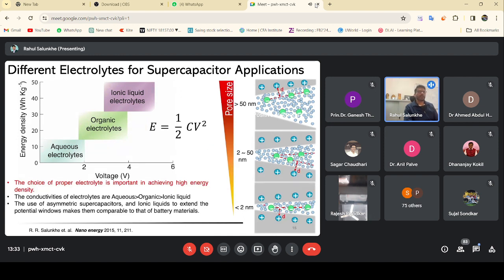So the very first requirement is the micropore structure, and that the ion size should match the pore size. When the ion size matches the pore size, we can achieve a very high capacity for any electrochemical device. This is not only true for carbon materials or non-aqueous electrolytes. This is possible for H2SO4 as well as any metal oxide. So if we take any material with a pore size matching the electrolyte, then your performance is going to be very high. This is the basic principle for improving the energy density of supercapacitors.